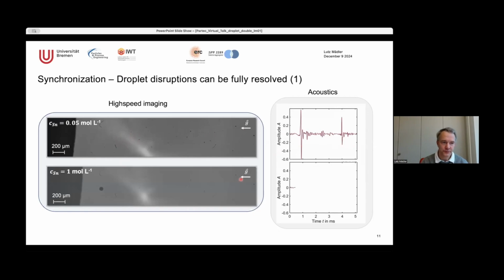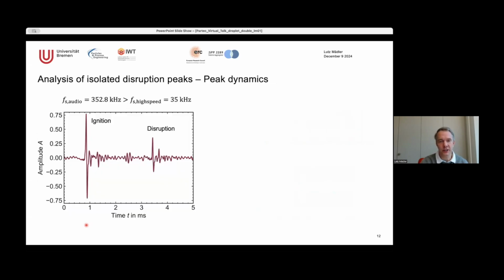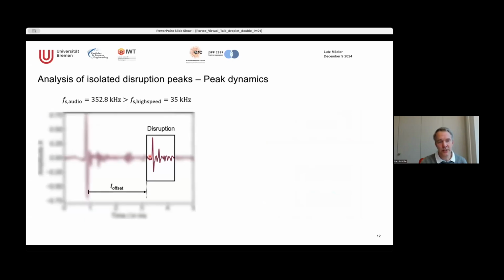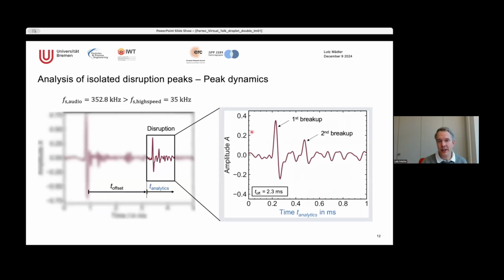With this, we have a very high resolution, because the high speed image analysis is even too slow for us sometimes. But with the droplet acoustics, we can actually look into the droplet explosions much better. And I believe in general in particle technology and spray technology we should do much more with acoustics, because the measurement frequency of acoustics is very high, and you get a lot of information out of this. So basically, we have here the acoustics of the droplet ignition. So really, when the droplet ignites, catches the flame, and then here we see the droplet explosion, and then we can zoom into this explosion event, and we have the breakup here.